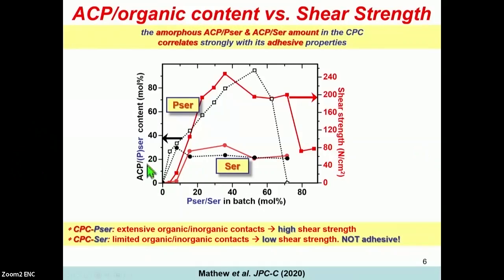we have plotted the ACP PSER content against the batched phosphoserine content in the cement. And the amount here was obtained just by deconvoluting phosphorus-31 NMR spectra. Then you can compare, well, these are the contents of ACP PSER. You can compare the results with the data in red here, which is the corresponding shear strength for the cement. And you can see that the shear strength remains high whenever the ACP PSER content is high.